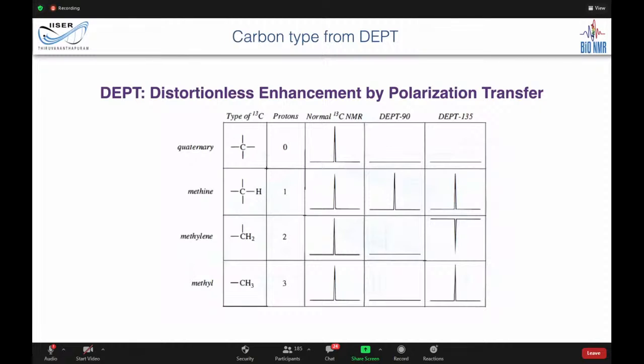DEPT is very similar to INEPT. The only thing is there is a 90-degree pulse at the end on the proton, which determines whether you see a methine, methylene, or a methyl. Of course, quaternary carbons will not show up in DEPT because there is no INEPT there, so they'll be blank. With DEPT 90, you get a positive signal for a methine, and for methylene and methyl there will be 0 signal. But for DEPT 135, you get a negative signal for a methylene, CH2, and a positive signal for methyl. In this way, you will be able to distinguish between methine, methylene, and methyl.